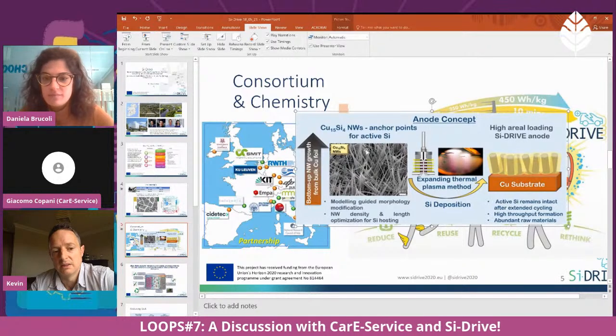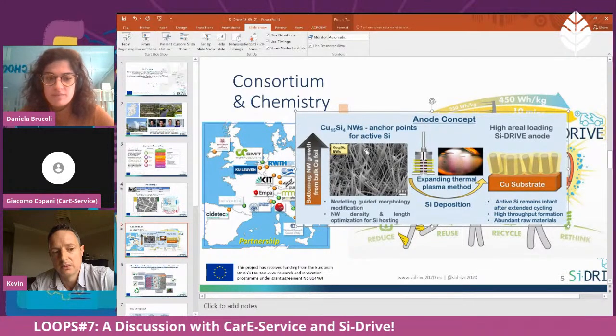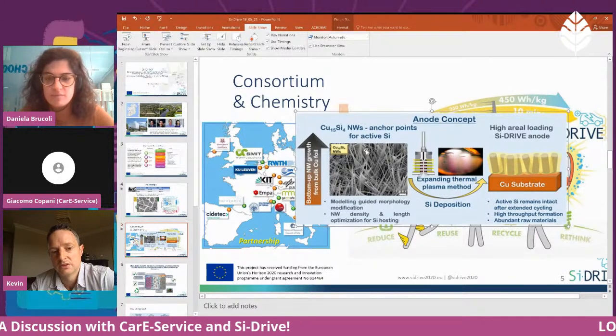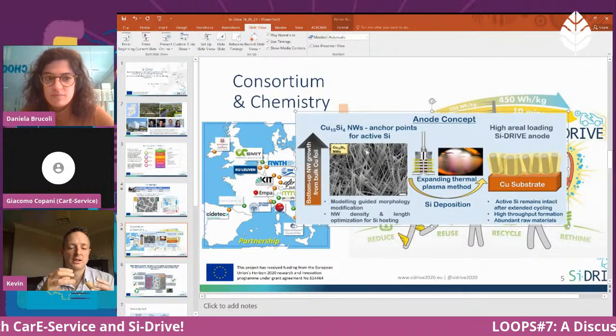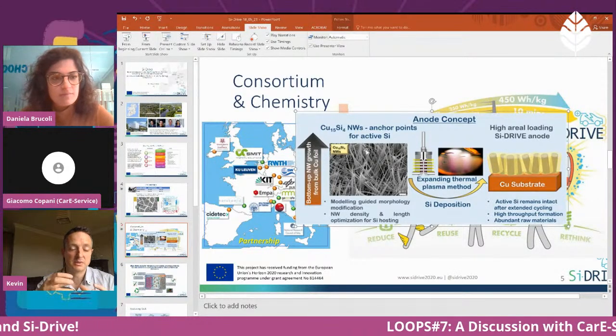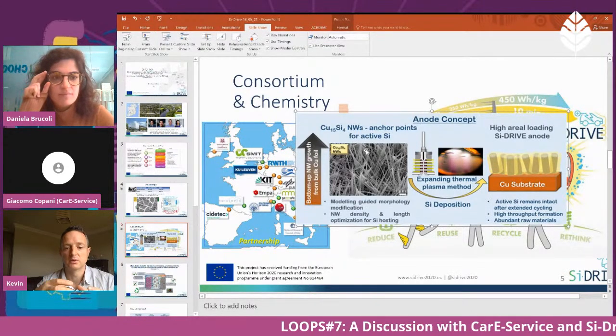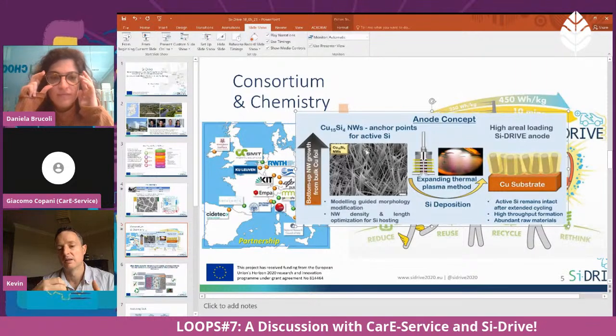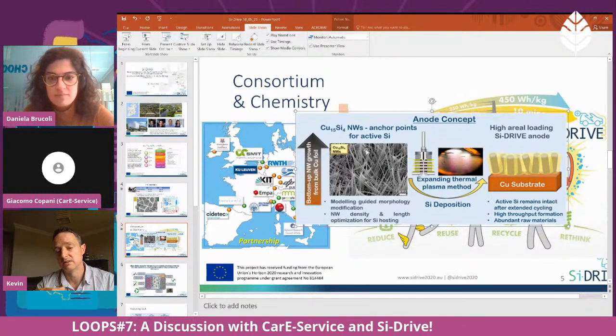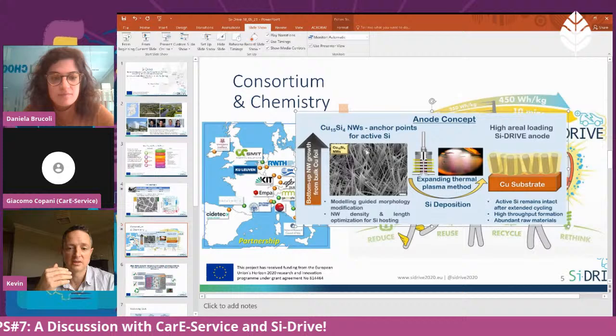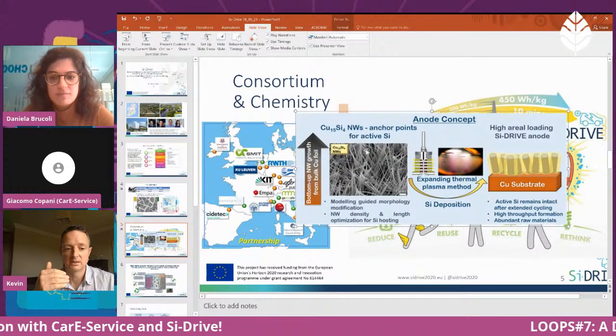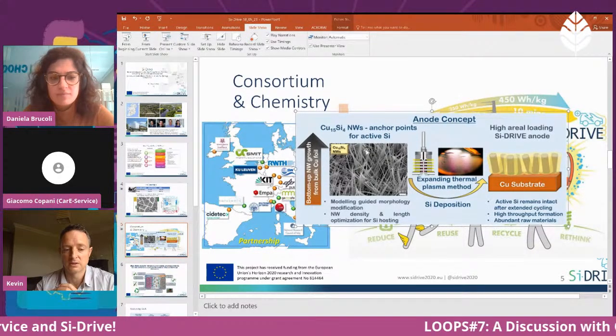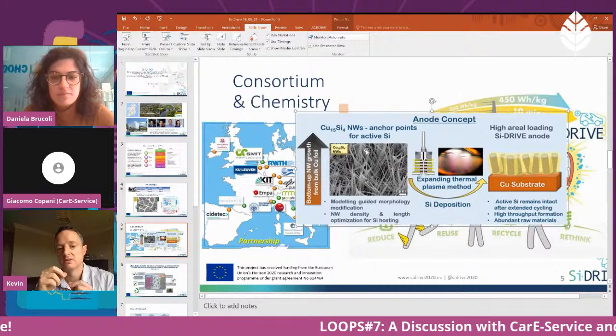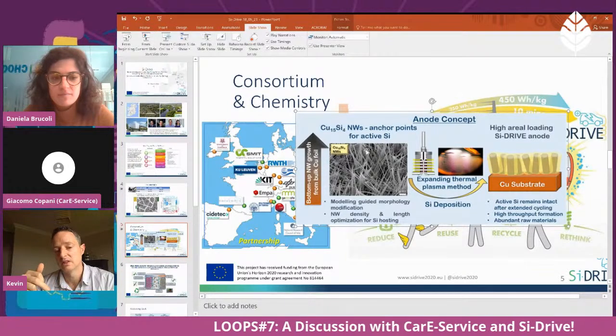And then with our industry partner in the Netherlands, Smit Thermal Solutions, they have a plasma enhanced CVD process, which can deposit silicon. So the silicon then deposits onto these nanowires. Now, if you just deposit the silicon, for example, onto the bare copper, we get cracking similar to what I showed in the previous slide. But when we deposit it onto the nanostructures, it radially coats the nanostructures.